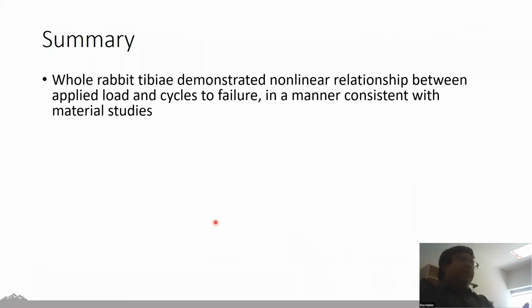So the first thing we noted in the study was that when we're looking at the whole bone level in rabbit tibia, we certainly saw a very nonlinear relationship between the applied load and the cycles to failure in a way that really is consistent with what we expected based on material studies. And this is a very important result, especially as biomechanists who maybe don't always want to run a finite element model. And it's a very encouraging result, I think. It means that if we're trying to find ways of helping people, we only need to make subtle improvements to the loads that their bones experience, in order to get big impacts in terms of fatigue life.